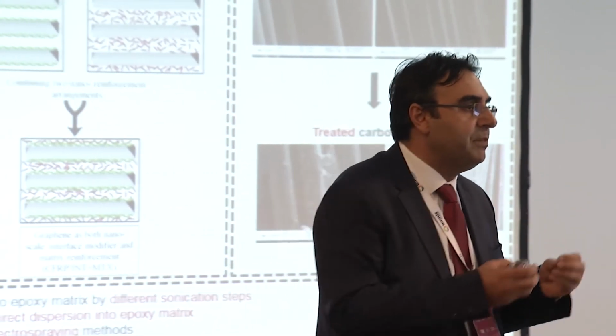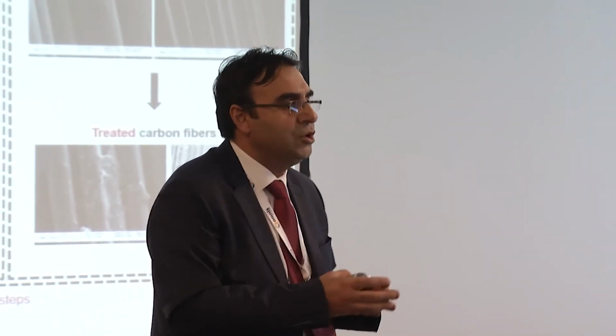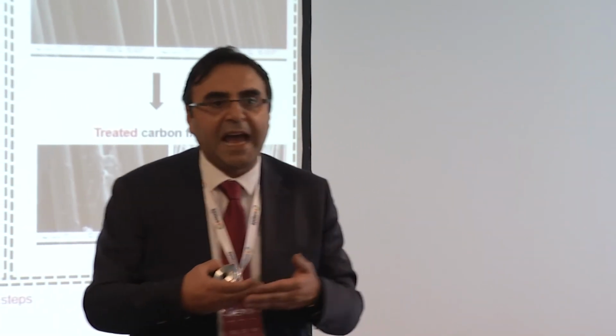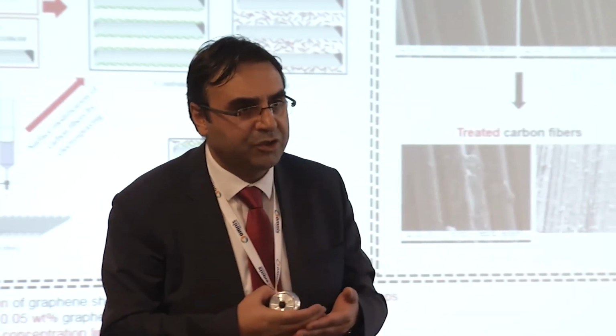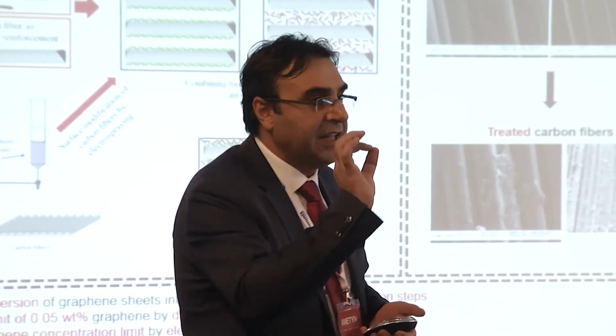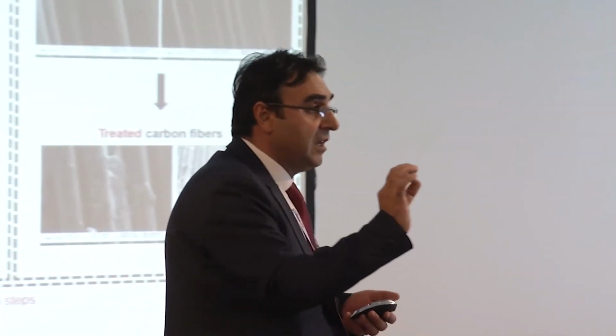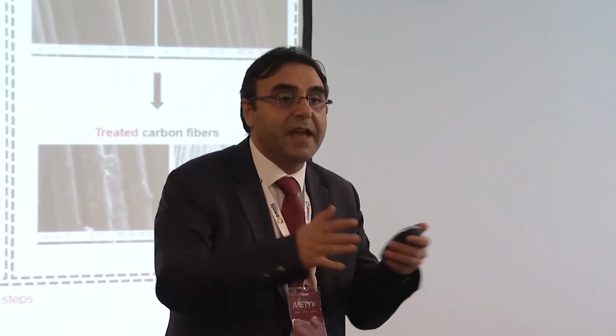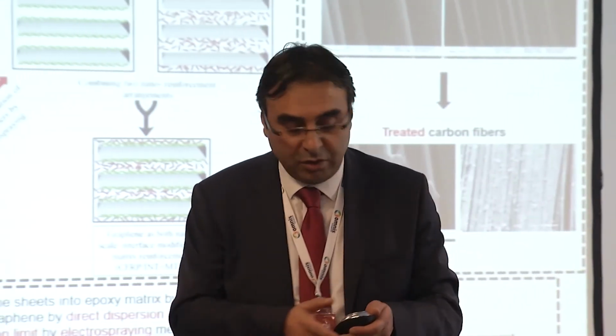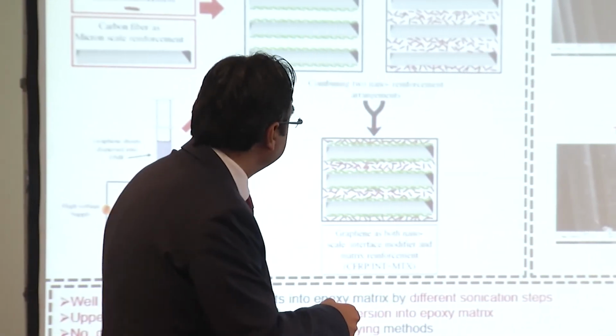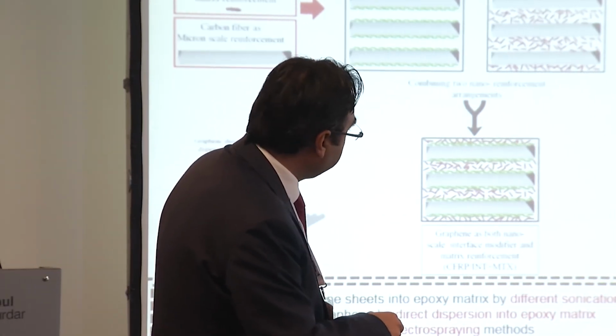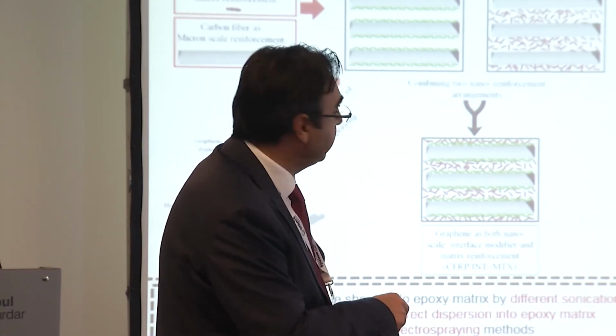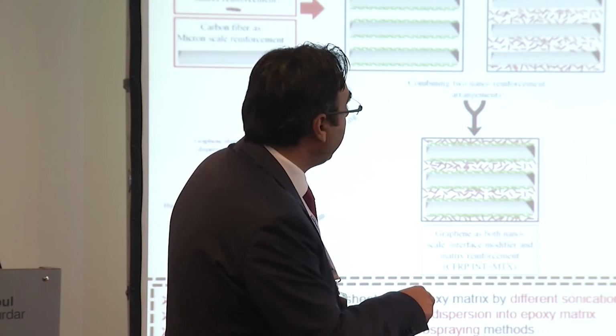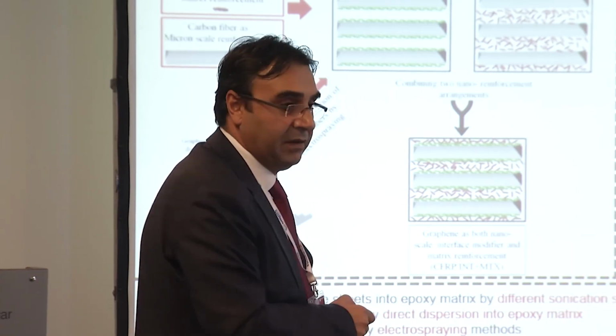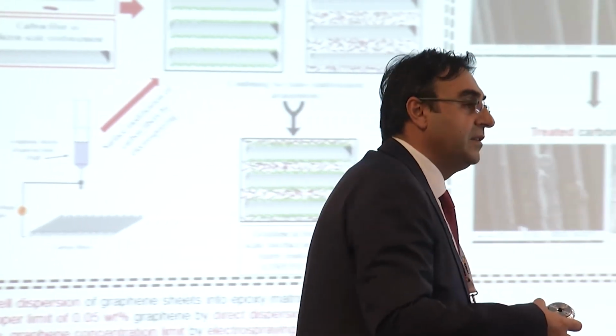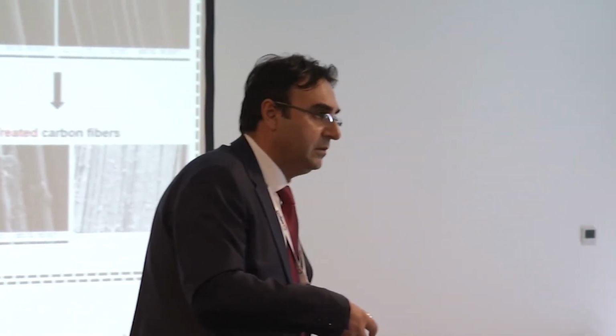And instead, to be able to beat the surface tension, we said that we should use an electric field, because the electric field acts in the opposite direction to the surface tension. So you form a Taylor cone that gives you a very refined jet, so you can distribute your graphene in a very controlled manner. That is the reason we incorporate it onto the surface of our material. You see the attachment of the graphene sheets to your carbon fiber, and this is a zoomed-out view, and it is nicely covered. We also integrated this graphene into the epoxy as well.